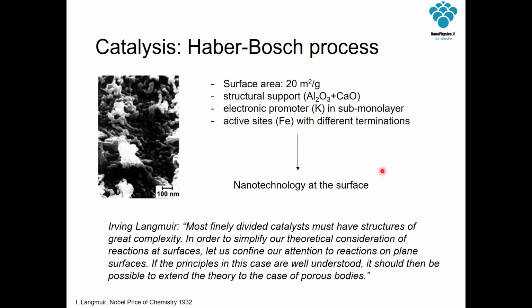That's a little bit more our ambient. So this is such a catalyst in this Haber-Bosch process. Now you see this is an electron microscope image. You see the scale here, 100 nanometers. And you see there are tiny particles here between 5 and 10 nanometers in size, which is actually this iron catalyst part. So we have a large surface here.